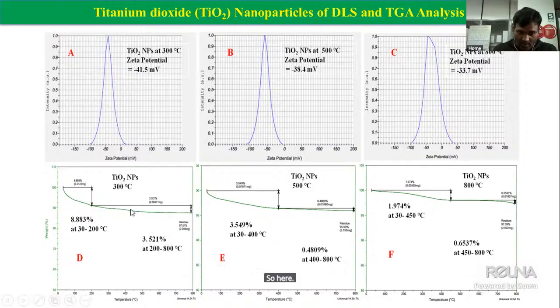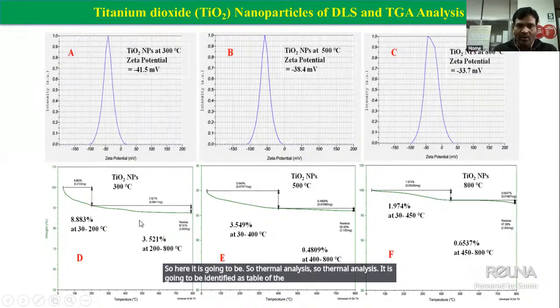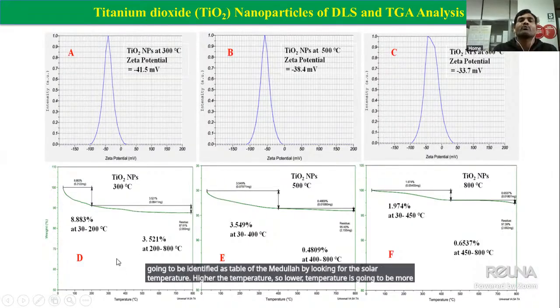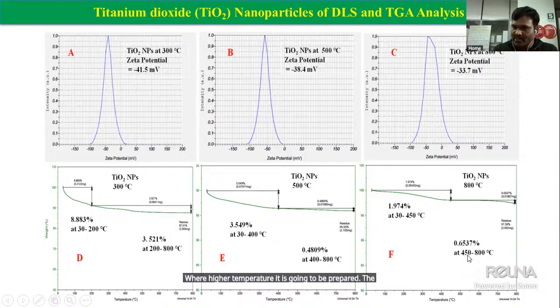So thermal analysis identifies the stability of the material for the lower temperature and the higher temperature. At the lower temperature, more weight loss occurs, whereas at the higher temperature the material is well prepared, so the weight loss is less.